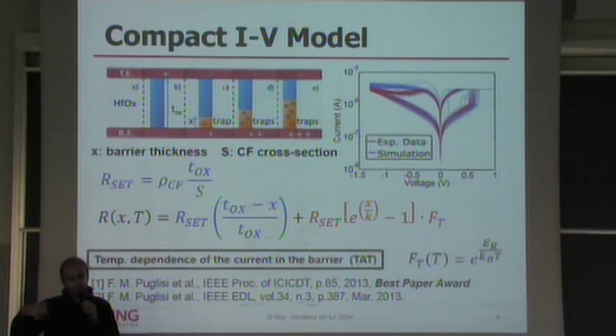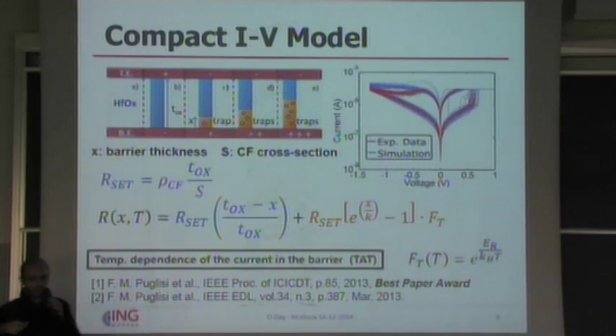It took a while to develop the complete model, of course, but it's really based on a simple assumption. Here you can see the schematic depiction of the device in the pristine as-fabricated state. It's an insulating structure. Then, as I told you, we control the breakdown, and we end up creating a conductive filament, which determines the low resistive state of the device. This is the low resistive state. This is an ohmic-like conductive filament, and the charge transport in this regime is ohmic-like. Here we are on a logarithmic scale, but trust me, this is linear, this is ohmic.